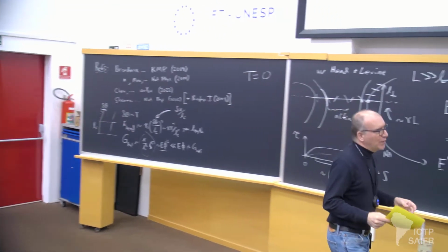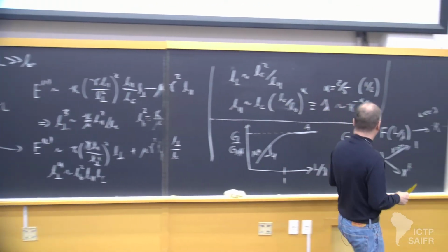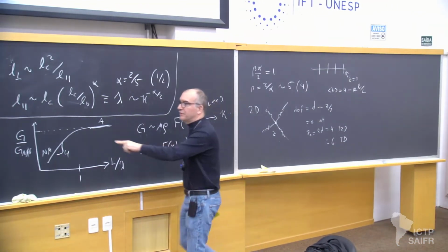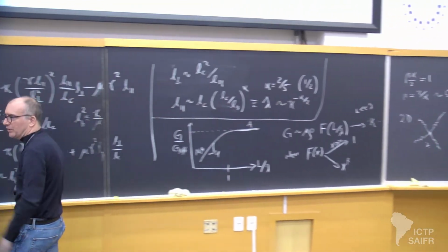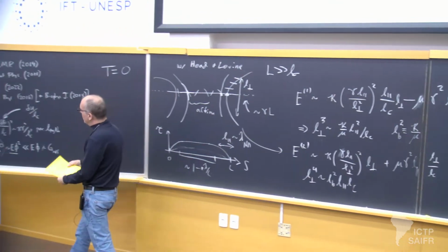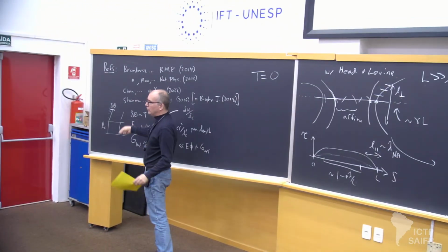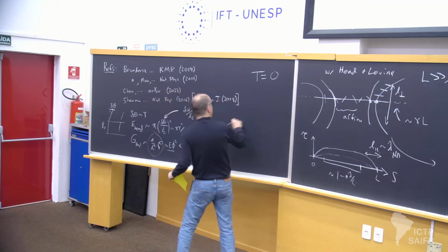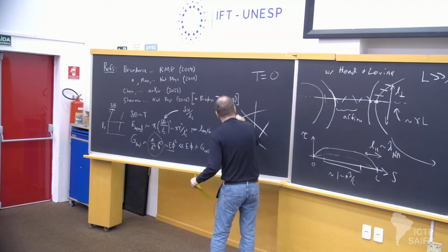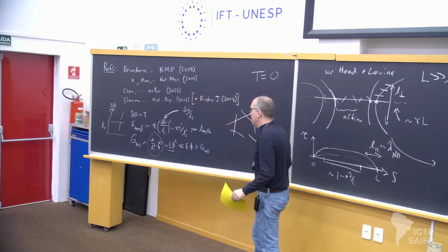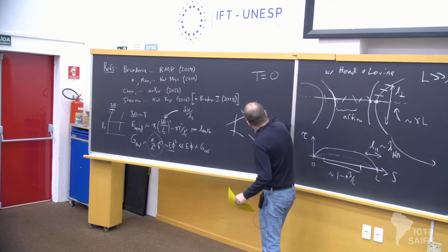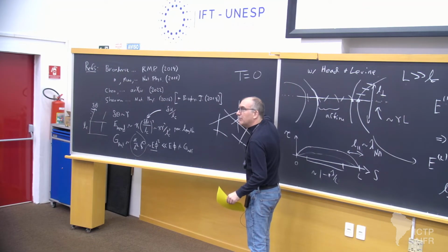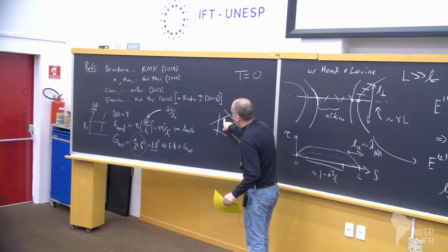Exactly. So here's the problem. This function definitely changes for different architectures. So that's why I don't want to call it universal. If I simply go from a lattice structure in 2D to what's called a Mikado model, Mikado is like the game, you just throw down rods at random in 2D. The Mikado model has junctions which can be really, really close or far apart.